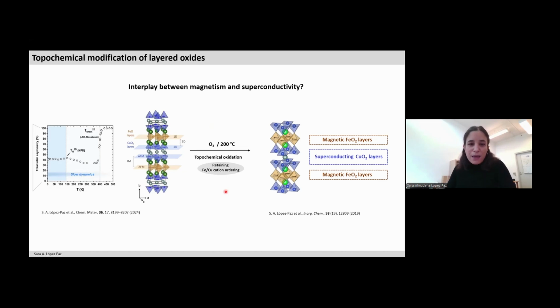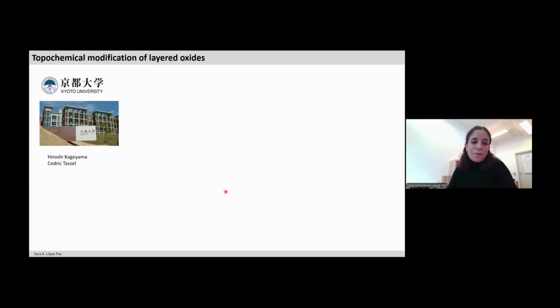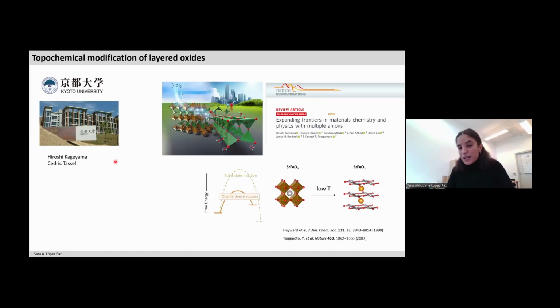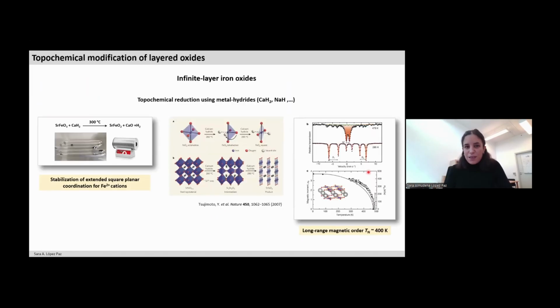And to learn more about this, I moved to Japan for a short-term stay to the group of Professor Hiroshi Kageyama, where they were actually pioneers in developing these methods to attain more controllable ways of preparing complex solid-state compounds. And in particular, they were very interested in developing topochemical reduction approaches. So here, what do I mean by topochemically? What we would like to do is to retain the structural topology of our lattice intact by working at a temperature where we can only allow the anions to move while the cations remain frozen. So this is something they were working on for quite a while.